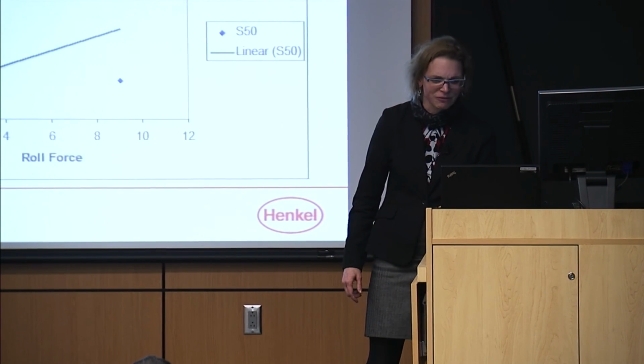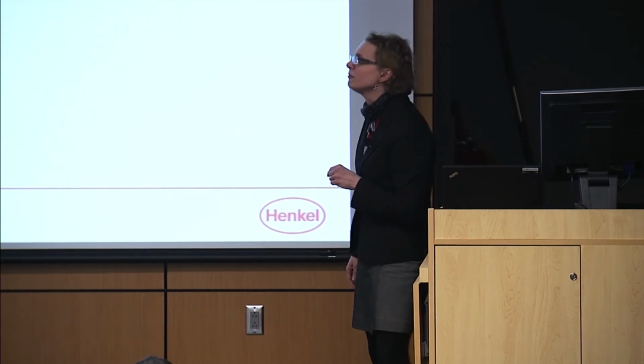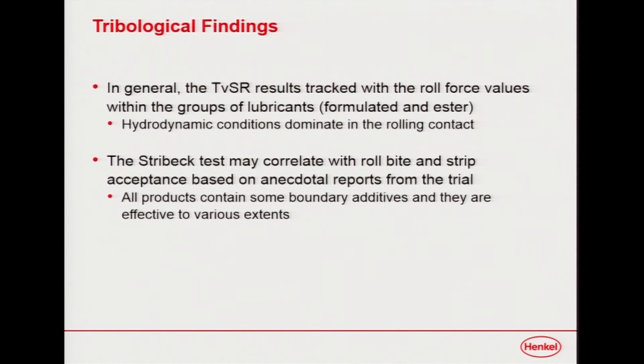We kept going, we didn't find very much. But what we did find was that our traction versus slide roll, so this one specific test we were playing with, really tracks well within groups of base oil. So as long as we minded our chemistry, very, very closely minded our chemistry, we could do extremely well with predicting the behavior in the mill.